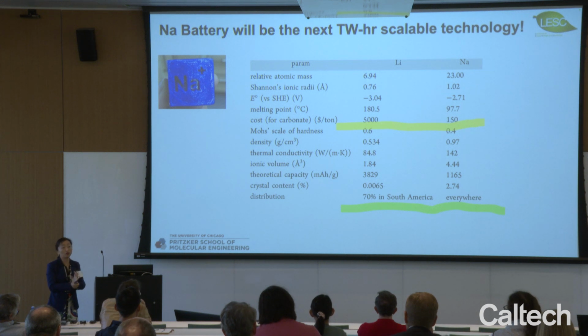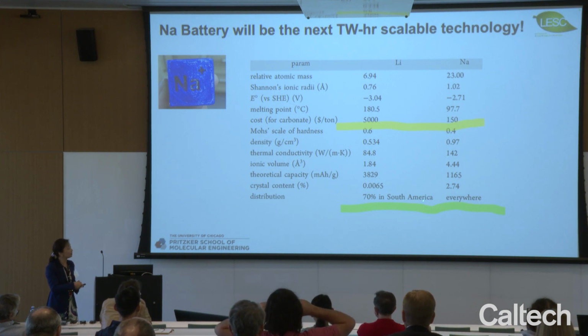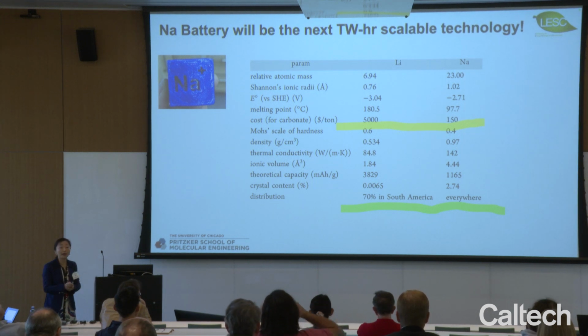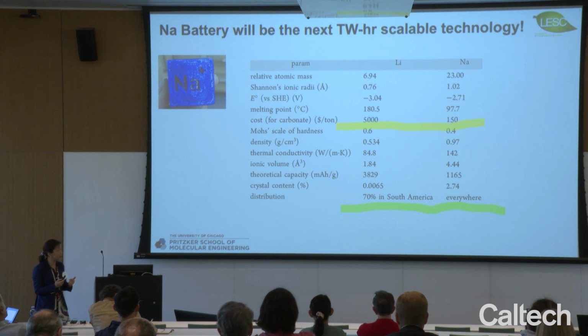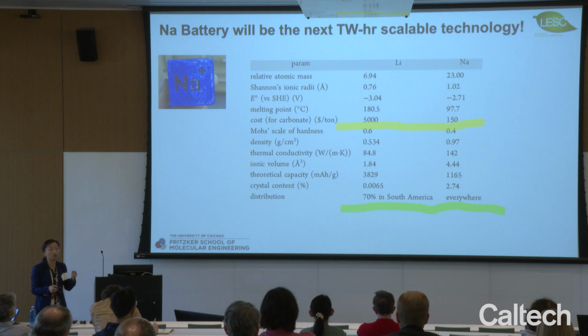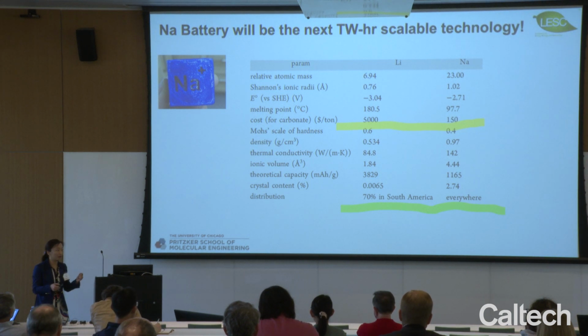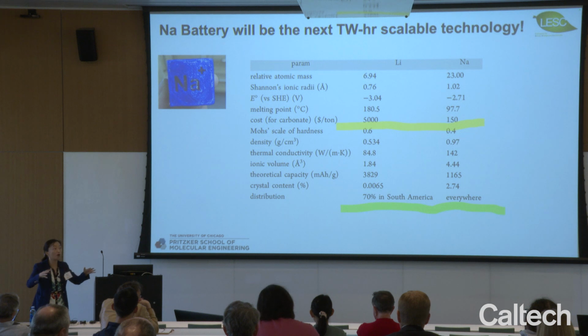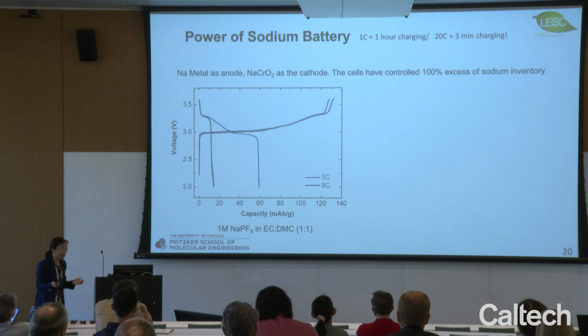Now, when we talk about grid storage, of course, the priorities change. And then the other important thing is really the distribution. And I think sodium batteries in the recent 10 years have returned to the research scene. I also want to point out the low melting temperature caused a significant concern about sodium safety. But I want to say when we look at reactive metal dendrite formation, sodium is more difficult to form dendrites because at room temperature it always tends to smooth out because of the low melting temperature. So sodium actually came back to our research field starting about 2012, and in the last 10 years I want to show you some interesting development work that happened in my research group, the power of sodium batteries.